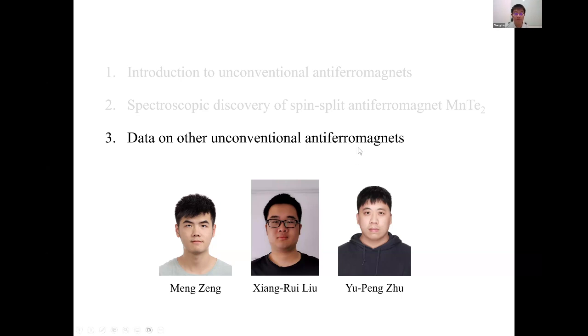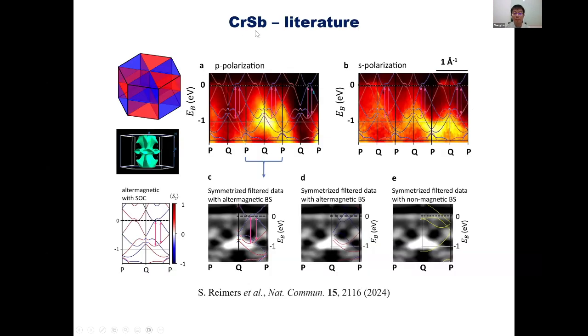I can talk a little bit about another work of ours, led by the student Meng Zeng. This work is on chromium antimony, CrSb. We have a paper on the ARPES data on chromium antimony. You can see here that the spin splitting is kind of visible, but the problem is it's not that visible actually. So this data is not very optimistic. A lot of groups tried to repeat these measurements to get better data on this compound, including our group. Our data is like this.